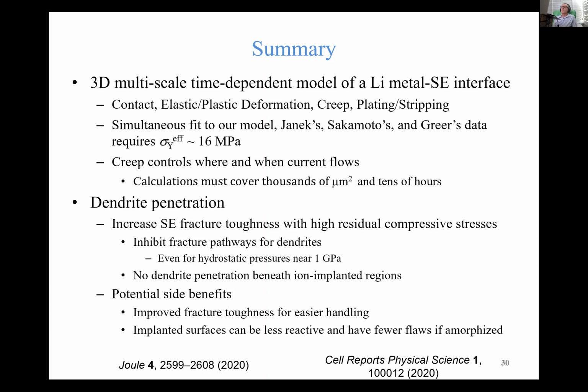And so the calculations we claim have to cover thousands of square microns and tens of hours if you're going to be realistic. If you're looking at just one dendrite, you're not looking at a representative volume element. The second part of the talk was about dendrite penetration, and our panacea, the way we think you're going to solve this in general, is you increase the fracture toughness of the solid electrolyte with high residual compressive stresses. And the idea is that this inhibits fracture pathways for dendrites. If there's no crack, the dendrite can't go anywhere.